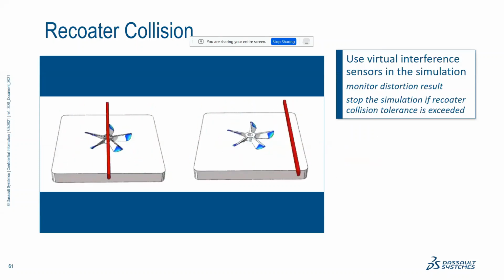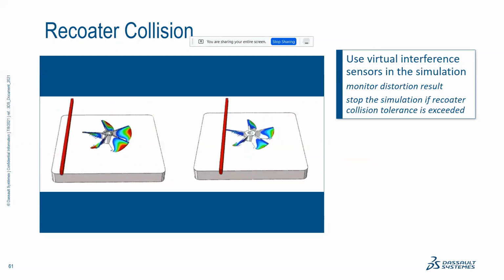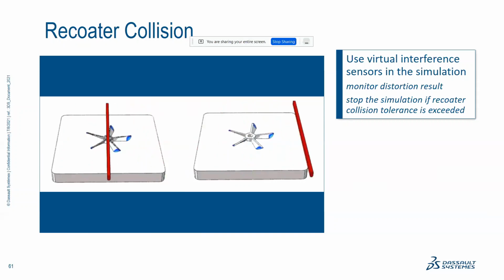So we can also virtually incorporate sensors, monitor the distortions. Like say you have in this case an impeller blade, which is being printed. So we are printing this blade, and what can happen is, say, for certain design orientations or support structure which are lacking, say in the case of the right side, one of the blades, as it is being printed and without support structures, is started to warp.